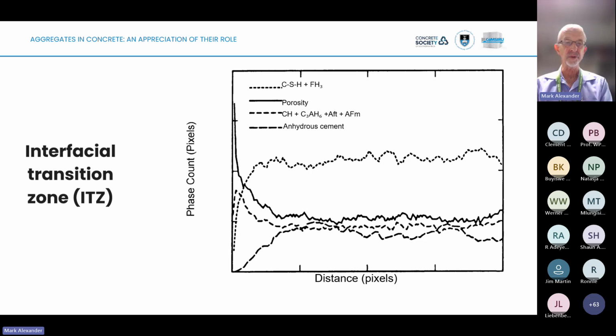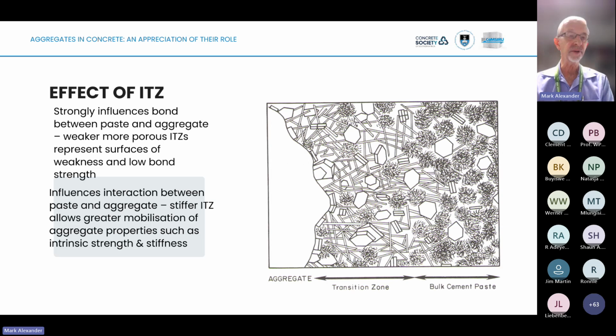So this zone can be very porous. It can be of low strength. It can be low stiffness. And the consequence is that it strongly influences, first of all, the cement paste aggregate bond. And secondly, maybe even more importantly, it influences the stiffness of the whole system. Stiffer ITZs allow greater mobilization of the aggregate properties, and we'll see that just now. So the ITZ, we've realized in the last, say, 2 decades, is really a very, very critical part of concrete. And we've also learned how to control this zone. So we can control it if we know what we're doing.